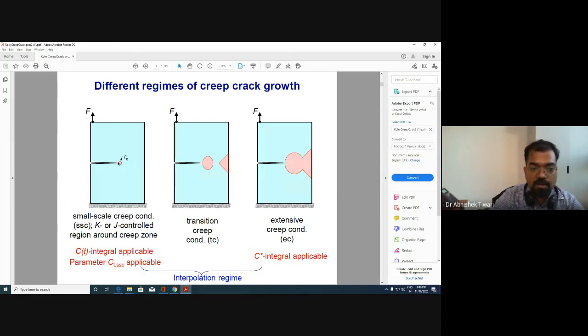So this is small creep zone, that means a very small area at the crack tip is deforming time dependently, and you are not changing the force, you are not doing anything, you just have maintained at high temperature. What is happening is that this zone where the material is deforming, which is dependent on time, that zone will be increasing. Because with time this deformation is coming into picture, so as you give more time, this zone will be getting larger and larger. Now what is this triangle at the back side? This triangle is coming because you're trying to open up this material. So once you are trying to open up that material, the back side of it will come in compression.